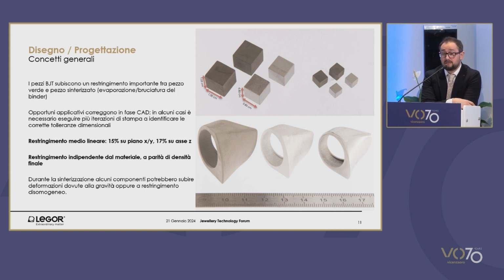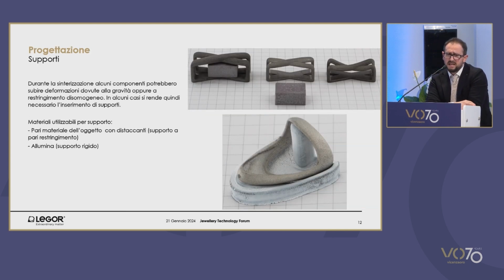But on top of that, you have to think about the possible softening of the piece and the presence of gravity, which plays a role also during sintering. This means that if the item has not been adequately placed in the sintering oven, it could be distorted by gravity, or the shrinkage in areas close to parts that have a bigger mass could actually be strained in an irregular way, leading to undesired distortion. To tackle this problem, during the design phase, it is possible to